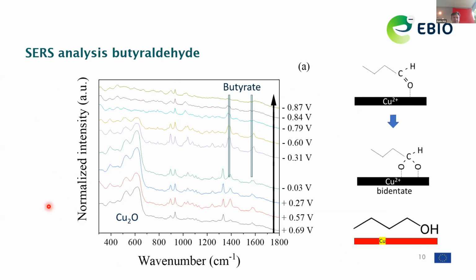So therefore, we resorted to Raman spectroscopy. I'll not go into a lot of detail in the interpretation of all the Raman bands that you see in this particular spectrum. I just like to point out a couple of bands that you see forming as a function of potential. It is also important to realize that if you are dipping your electrode into the reactant solution, that initially the surface of the copper is passivated by a film of copper oxide. And you can actually spectroscopically resolve that by this sort of broad feature that you see in this region of the spectrum. And of course, if you go negative in potential, you see these features disappear, right? They're almost gone here. And that means you have reduced the copper oxide towards metallic copper. So that's one thing that we clearly see happening.